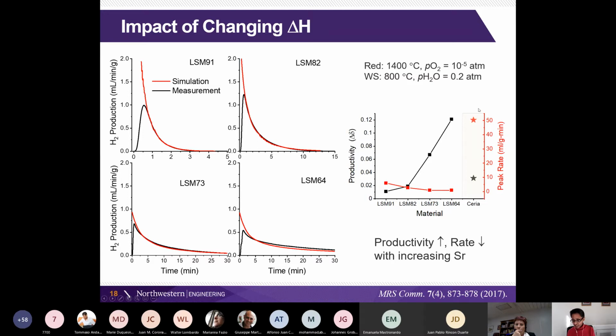And if we compare that for ceria under the exact same conditions, where we do a reduction of 1400 degrees Celsius and water splitting step of 800 degrees Celsius, these points are almost reversed. This is not a mistake in this plot. The total amount of productivity is quite small for ceria under these conditions. It really doesn't get reduced very much, even under equilibrium. But the rate at which that hydrogen would be produced, because we'd be going to 800 C, where the driving force for oxidation is very high for ceria, that initial peak rate would be extremely high. So this is the trade-off that we need to understand.